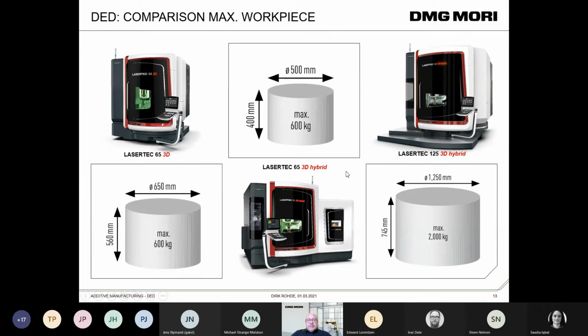Working areas: hybrid, 400 millimeters height. It's a little bit less than the DED only. This is a non-hybrid machine, only for DED work. That's resulting from the laser head. We have a little bit reduced height and a 500 millimeter diameter roughly. And the Lasertec 125 is almost 750 in height and has 1250 millimeters in diameter, up to 2 tons.